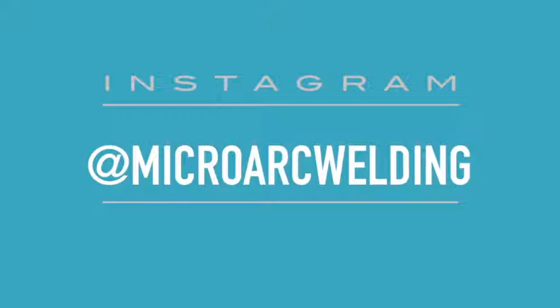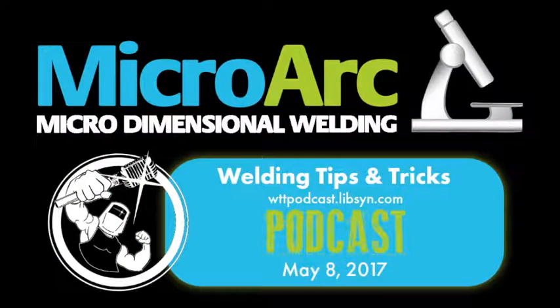Yeah. I'm curious, because you just mentioned welding using a stereoscope and whatnot. What power source are you generally using, and what amperages are you using, your tungsten diameter and all that stuff? I wonder if you can clue the audience in on some of that. We basically use a 16th tungsten. Our power source will go up to 100 amps. It has a dual range power source from 1/10 of 1 amp to 10 amps, and from 1 amp to 100 amps. But it has a 70 amp continuous duty cycle, but it will weld up to 100 amps for a short amount of time.